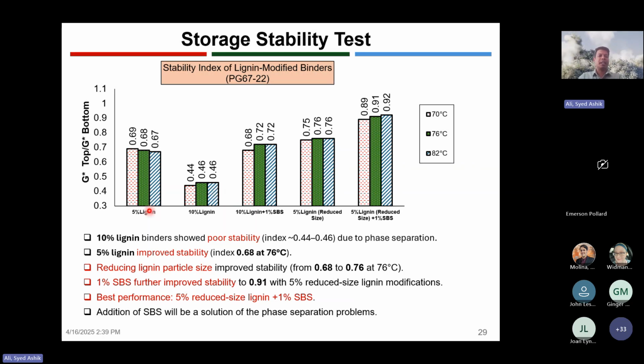But with 5%, we see that there is some improvement in the storage stability, around 0.67 to 0.68. But still, this is not enough. This is not very close to 1. So what can be done in that respect? We have taken two approaches. One is to reduce the particle size of the lignin, which Dr. Lynam has already described.